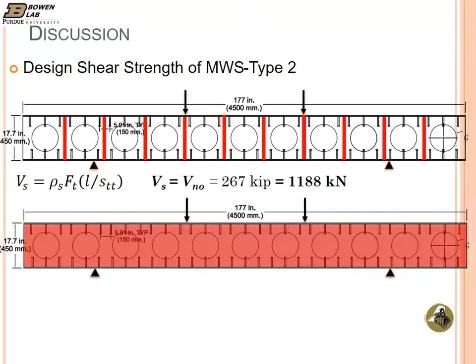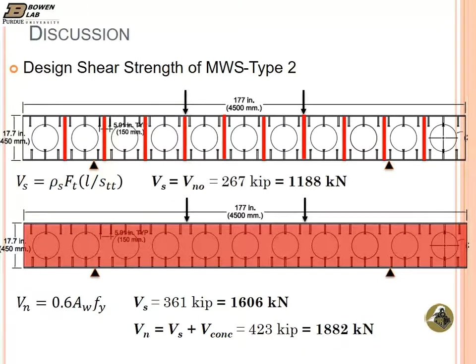But instead, because this web plate has a lot of steel there, it's almost working as a continuous web plate. So I can find the equivalent continuous plate by subtracting the hole sizes. You remember this plate was 10 millimeters, and if I subtract the volume of the holes, that would be equivalent to, let's say, a 7 millimeter continuous plate. And if I do that, then it almost becomes like a W shape, like a steel section. That way I can calculate the shear strength by just taking the web area, 0.6 A web times Fy, and that gives us 1606. Then I can also add the concrete contribution, which takes us up to 1882. So for this case, since the failure strength was 2300, this approach seems to be closer to the experimental strength that we observed.